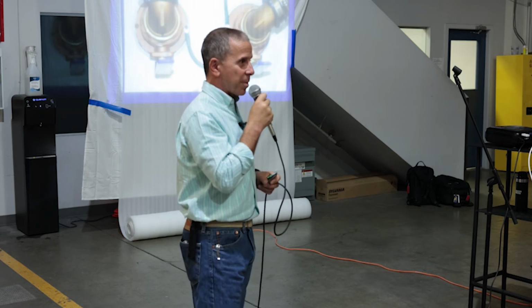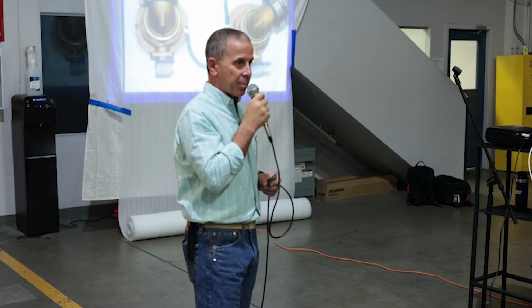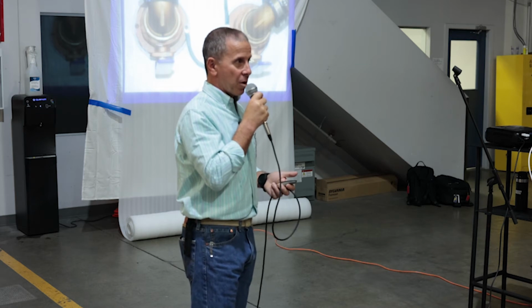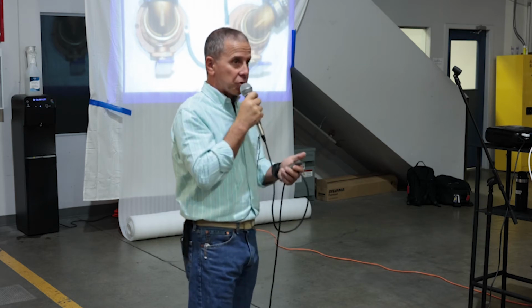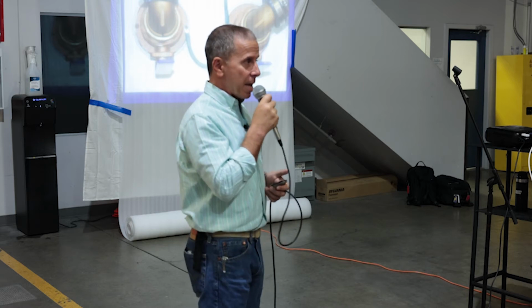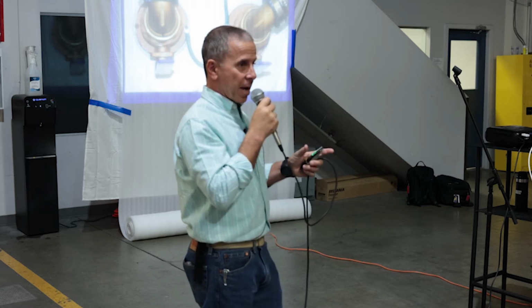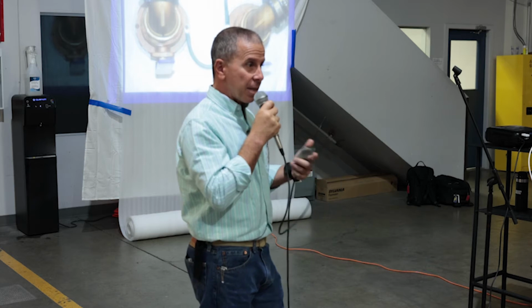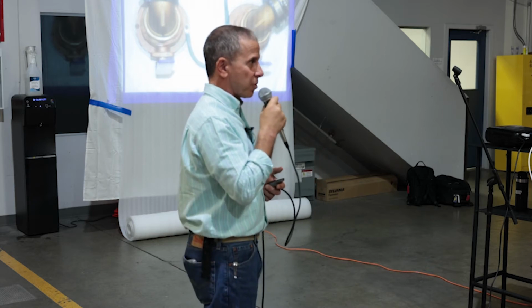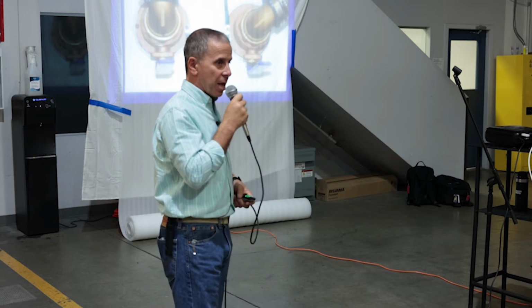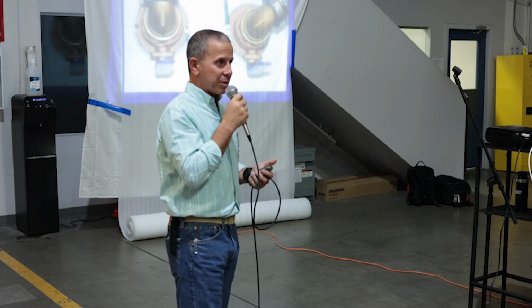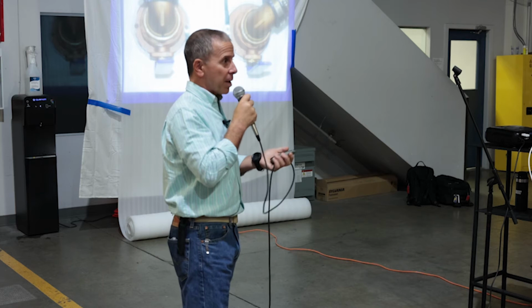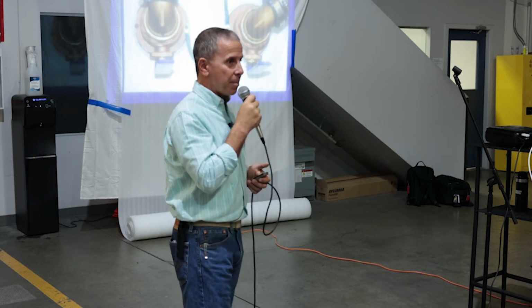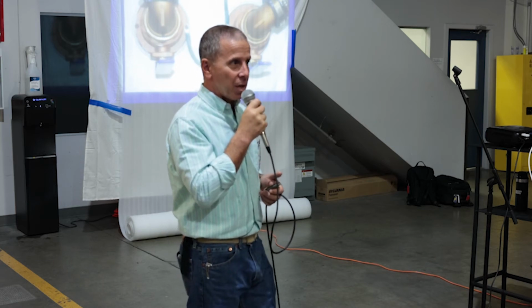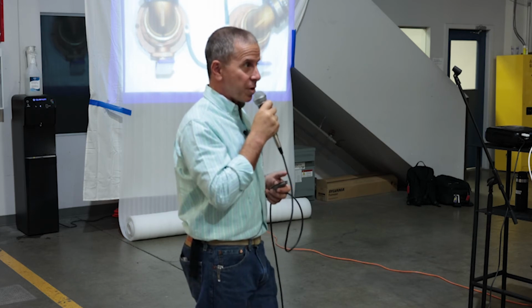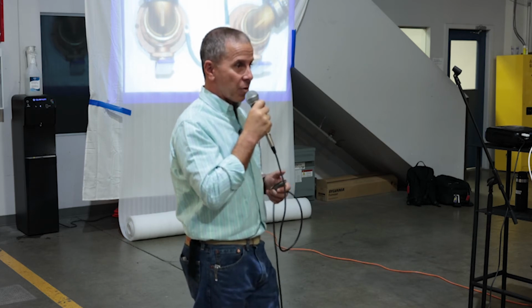So we really have to make sure that the contact between the metal that's being protected and the sacrificial anode is very good. Now that holds true for an aluminum vessel as well, in that if an anode is being attached to the hull and the connection is dirty, there's paint on it, there's corrosion on it, there's marine growth, and it is more than 1 ohm of resistance between that anode and the hull, we have now compromised the ability of that anode to protect the hull. So that surface needs to be extremely clean. Again, 1 ohm is a very low threshold for corrosion.